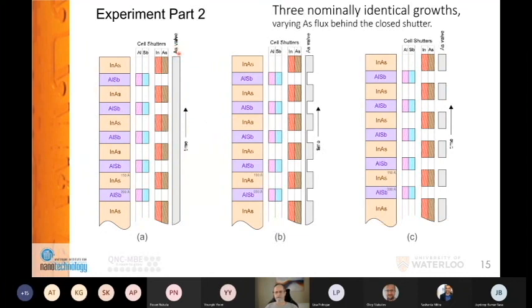the valve opening. So normally everybody grows this keeping the valve open because it takes time to close it. But we tried to have it partially closed and totally closed during the growth of the aluminum antimonide layers. And the design of the structure was made to make it particularly friendly for X-ray characterization. So we did use our